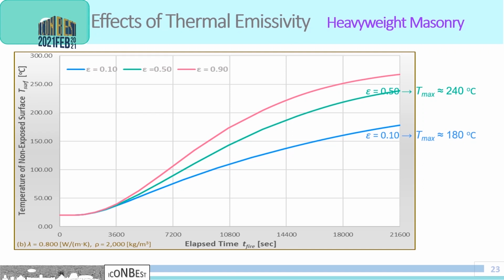In addition, from the graphs in this slide, it can be observed that variations on clay material properties affect the thermal response of heavyweight masonry walls in a similar fashion. For this case, the corresponding temperature values of the non-exposed surface are as follows. We have, for an emissivity 0.1, a maximum temperature 180 degrees. For an emissivity 0.5, 240 degrees. And finally, for an emissivity 0.9, a maximum temperature approximately equal to 265 degrees.